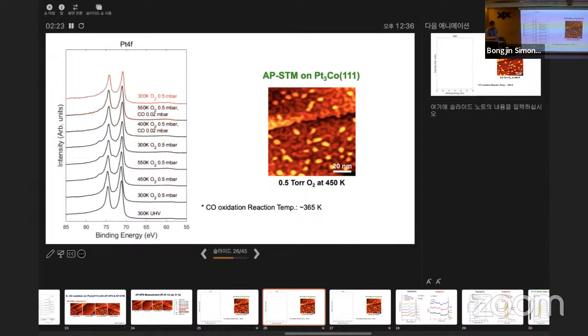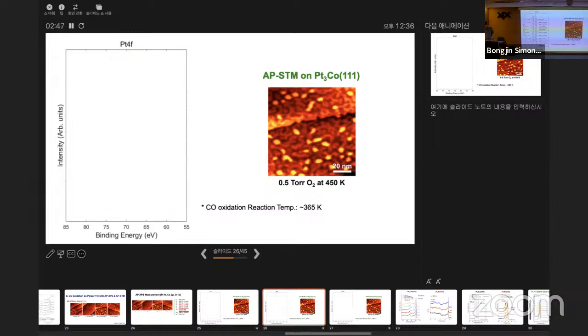And when we introduce a small amount of CO, as in the previous case, and then increase the temperature, this oxide is now completely reduced. And this oxide that is attached to the platinum somehow here is representing this state of oxygen that is actually reactive.